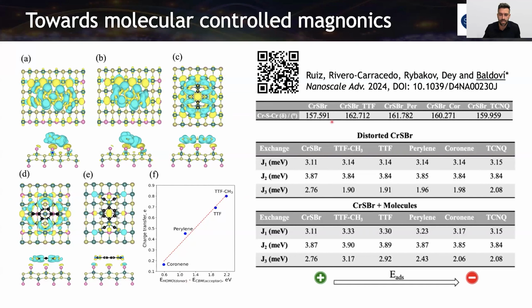Regarding the effects of the molecules, we can observe one thing. This is the chromium sulfur bromide, and along the y-axis this is the angle in the fully relaxed chromium sulfur bromide structure. The molecules are increasing this angle. This is detrimental for J3, because when we are increasing this, we are favoring the antiferromagnetic pathways, and especially when more donor is affecting more. And this has an effect here.